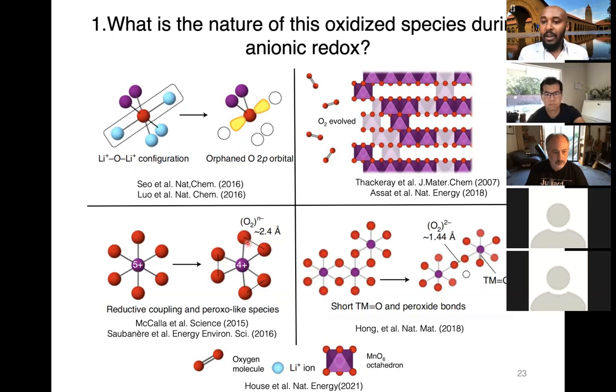There's a similar but different argument here, where instead of the oxygen atoms leaving the system, they are actually staying in the material by forming a short covalent bond close to 2.4 angstrom and forming this oxygen dimer as shown over here. And another argument that has been proposed recently by our group about 2 years ago is instead of forming an oxygen bond with 2.4 angstrom, we are indeed forming an oxygen bond with a bond length close to 1.45 angstrom. And in addition to that, we are forming a metal-oxygen double bond.